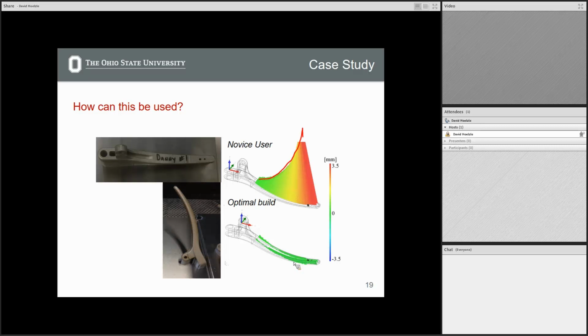And then after we pulled off the build platform, this is the distortion in our part. I don't know exactly what this is, but it's well less than a millimeter in terms of distortion at these far regions here, just by changing nothing but the orientation angle at which we print this part. Some other caveats: our print took much longer because it's higher, right? So that means you have to pass a recoater blade over it more times. That means you're using more powder as well.